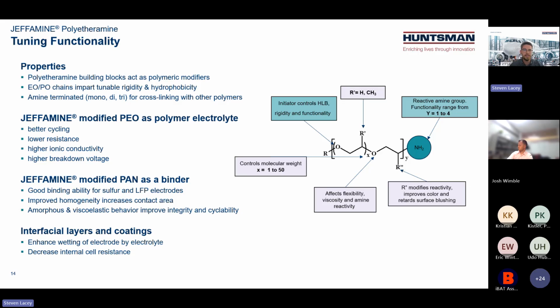So in this case, I listed a couple different examples where JEFFAMINE actually modified certain polymers to be used as either a polymer electrolyte or a binder. JEFFAMINE modified PEO also showed better cyclability and higher ionic conductivity compared to unmodified, due to the different tunability. I believe this one was a diamine, which also can be cross-linked to enable different functionalities and different performance. And then JEFFAMINE modified PAN was also used as a binder. In this case, it had a very good affinity with sulfur-based cathodes as well as LFP and improved the contact area and the homogeneity.